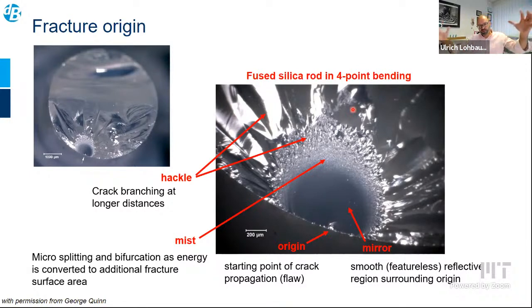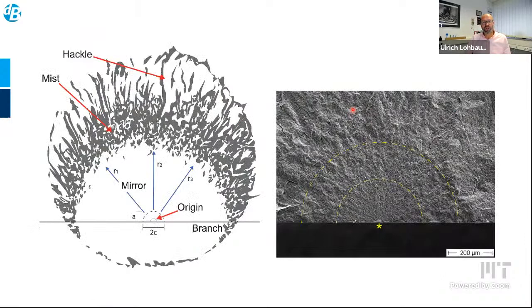But anyway, tracing back those features brings us to the point of the fracture origin, and we can easily locate the reasons for failure. So this can also be measured. There is also a relation that can be further investigated with Irwin's law on fracture toughness, where the strength of a material is related to the crack size, and the constant is the fracture toughness. So we can actually perform quantitative fractography on fractured surfaces.